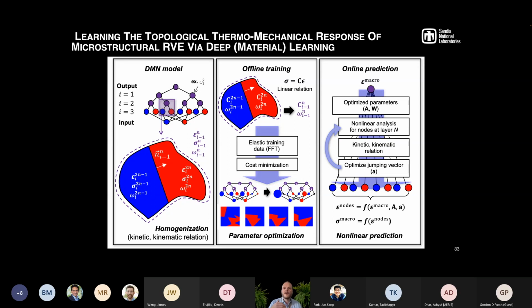The power of this type of network is that you train your network on elastic data, which is fairly cheap to generate. Once your network is trained on elastic data in the offline mode, then in the online mode, you don't need any retraining. Instead of using elasticity rules to come up with the effective relationship given by the network, you just need to change the constitutive behavior at the neuron level, again without any retraining, to be able to predict the nonlinear response of your RVE.